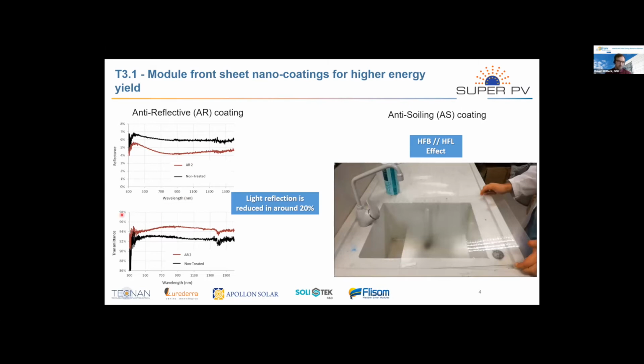And here at the bottom, you can also see the transmission measurements, so the transmittance as a function of the wavelengths. And here you can see again, black data is the non-treated glass, red data is the AR-coated glass. And you can see that this improvement in reflection is not only due to an absorption by the nanoparticles, but the nanoparticles also really enhance the transmittance of the glass. And this eventually will also improve your PV module performance.